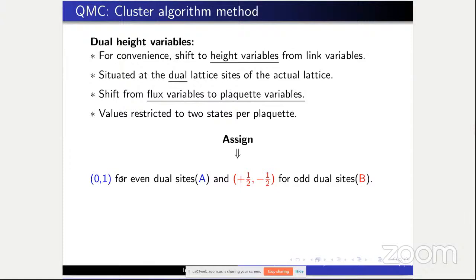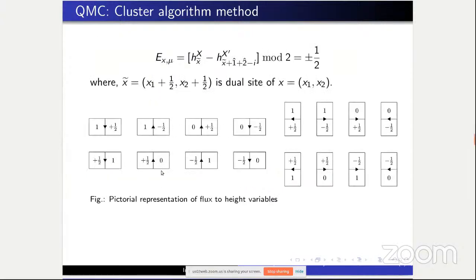Now, for the sake of the algorithm, we have shifted to height variables from link variables. These height variables are situated at the dual lattice sites of the actual lattice, that is, at the center of the plaquettes. So we basically shift from flux variables to plaquette variables. And since the flux variables are restricted to two states per link, the height variables are restricted to two states per plaquette. So we assign 0, 1 for the even dual sites A and plus or minus half for the odd dual sites B. This is the pictorial representation between flux and height variables.